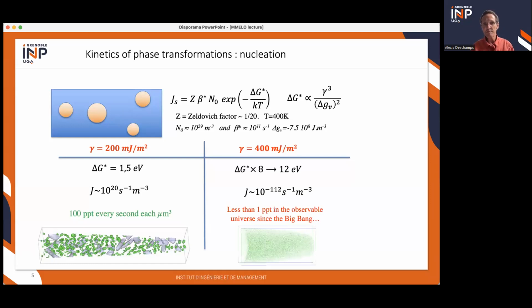So if you just multiply this interfacial energy by 2, then the nucleation barrier is multiplied by 8, because it goes as the cube of the interfacial energy, and goes to 12 electron volts. And in these conditions of temperature, the nucleation rate becomes 10^-112. So it means that basically you have 0 particles. Since the Big Bang in the observable universe, you will have less than 1 precipitate. So this shows you how sensitive this precipitation kinetics is to the physical parameters, and the necessity to find different ways to have realistic paths and trajectories to transformations.